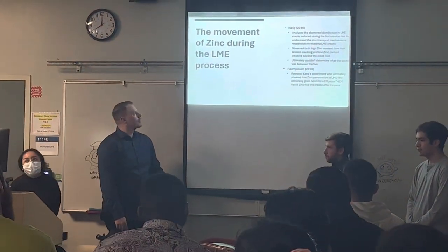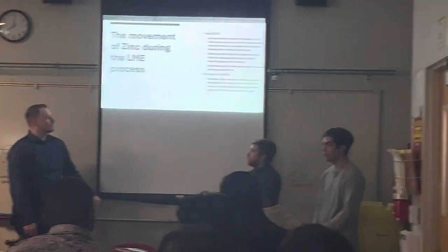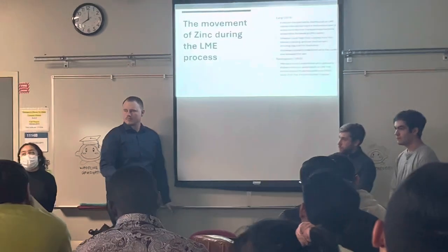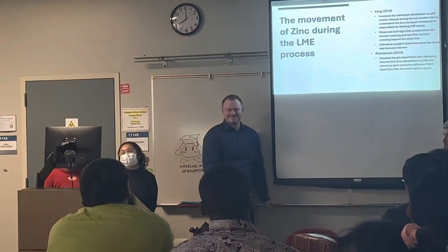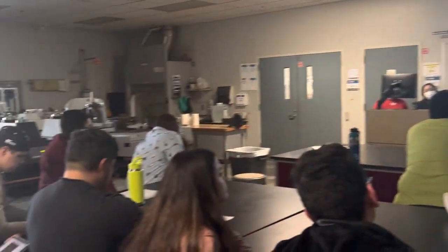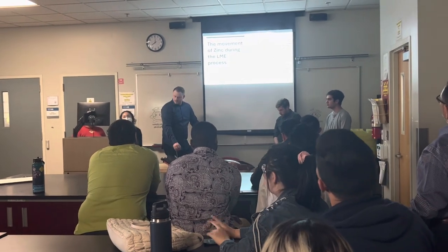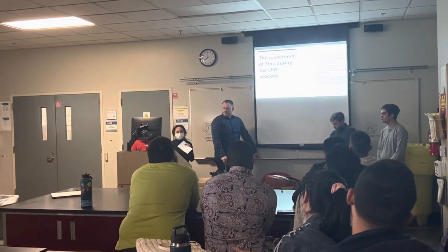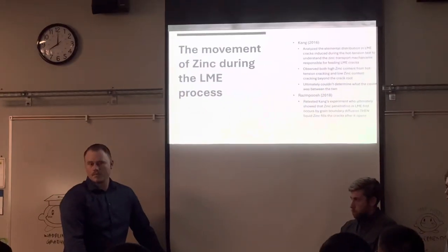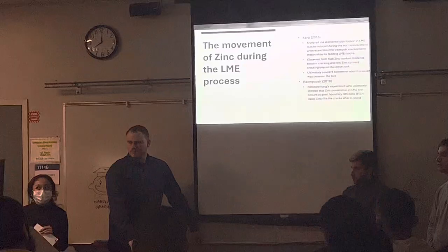And then for the movement of zinc during the LME process, it was first studied by Kang in 2016. He analyzed the elemental distribution of LME cracks induced during the hot tension test to understand the zinc transport mechanism that feeds the LME cracking. He observed both high and low zinc concentrations. The high zinc concentration cracks were happening on the top, while the low ones were happening underneath. And so he couldn't ultimately determine what it was.